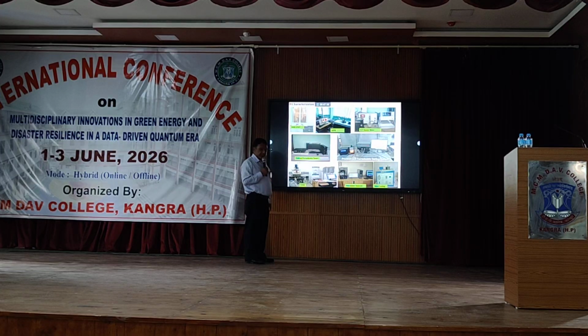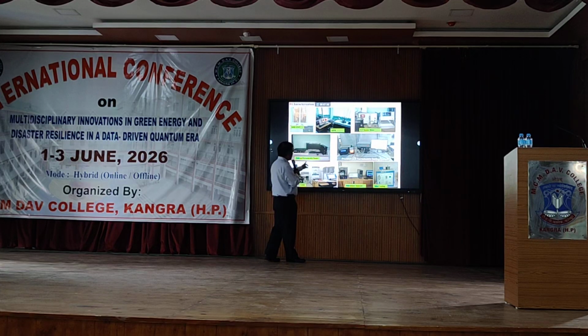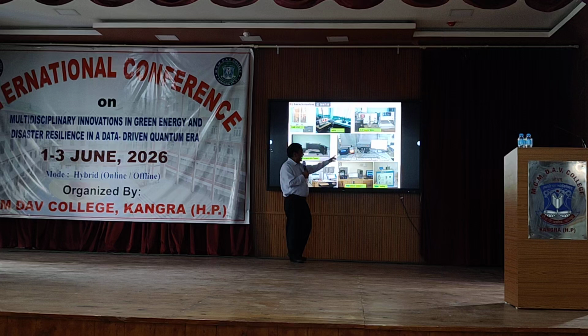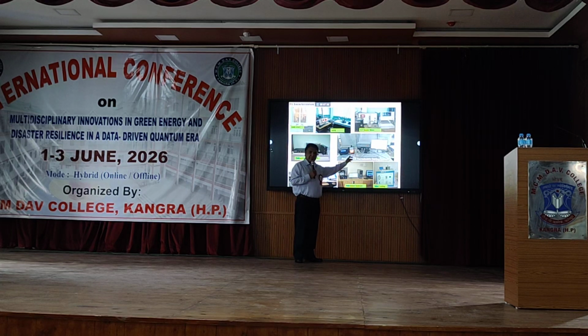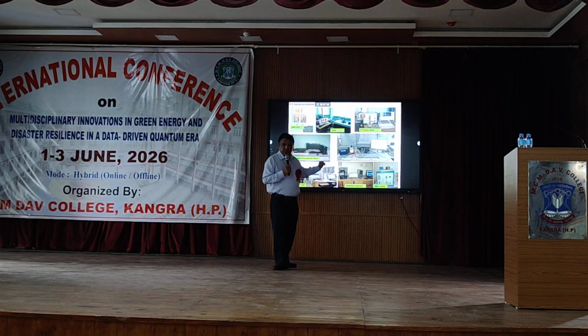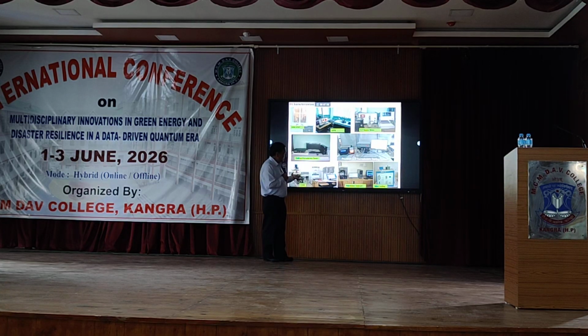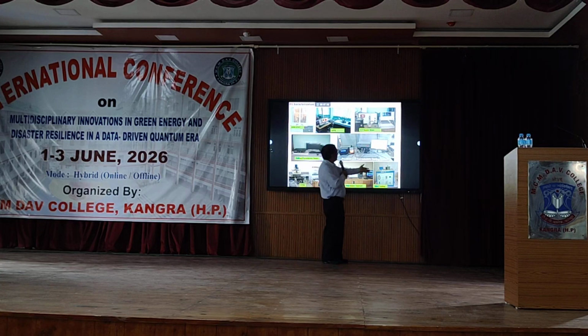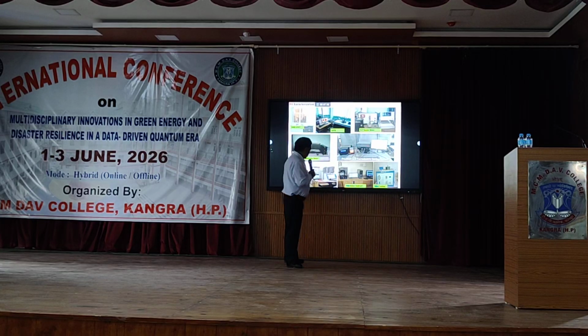in Himachal Pradesh University, where this one is a ferroelectric tester for thin films. Recently, 2 weeks back, we installed it with the help of ANRF. This particular instrument can measure piezoelectric, pyroelectric, and ferroelectric properties efficiently. This is a VSM for magnetic property measurement, impedance measurement, spin coating for thin film preparation, and this source meter to measure the leakage current of the material.